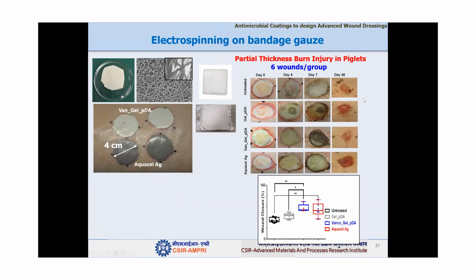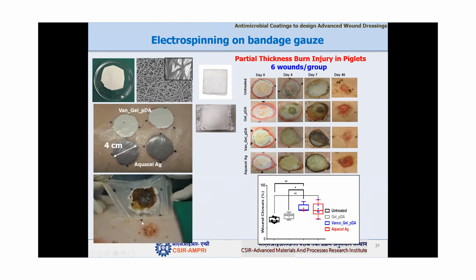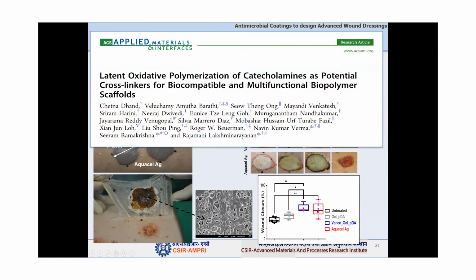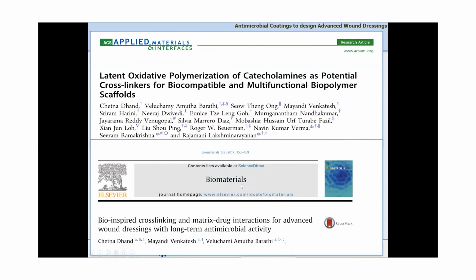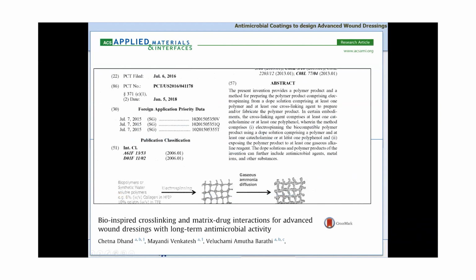So this is again the results, and you can see that again the antibiotic loaded dressings performed very good, comparable to the commercially available dressings. And this is the same dressing after removing from the wound. You can see that even during removal, there is no interference with the wound healing due to these dressings, and even the nanofiber morphology is retained after removing the dressing from the wound. So now they are very stable dressings. This is the paper we have published, in the ACS AMI journal, which is very good, and I think it is a rank 1 journal in biomaterials. We have published the study in biomaterials also, and we have an international patent on this particular work.